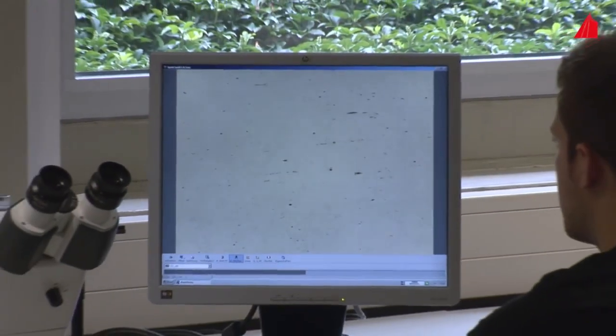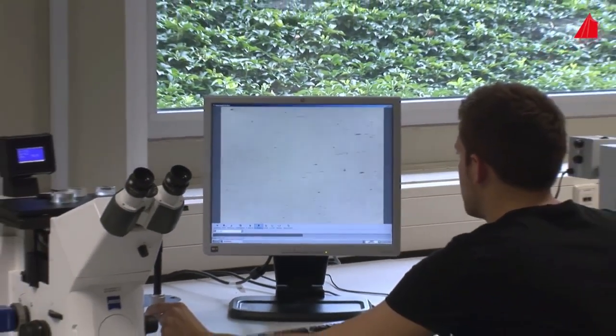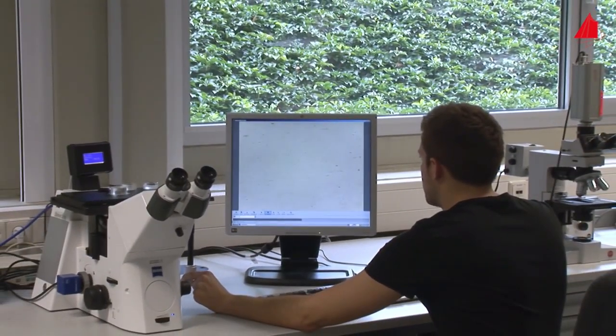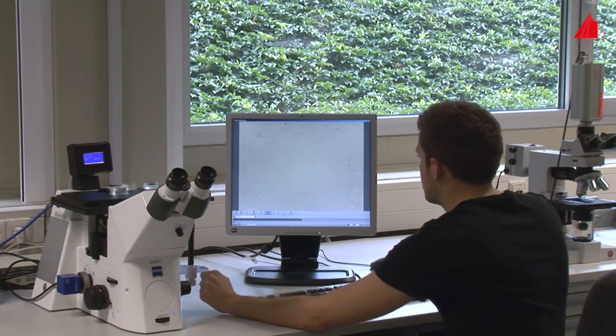In the polished state, there isn't much to be seen in this material. Only some elongated non-metallic inclusions can be observed, but if these inclusions are of special interest, then the polished state is the perfect one. Inclusions may best be seen here. However, if one wants to see the crystals, the grains and grain boundaries, then the microsection has to be etched.